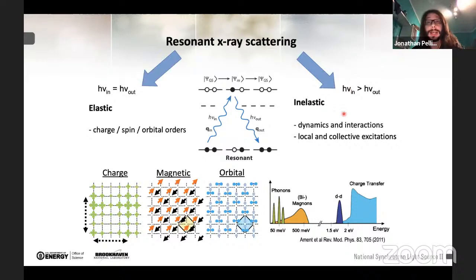On the other hand, when we perform resonant inelastic X-ray scattering, so the incident energy is higher than the outgoing energy, which means we leave the system in an excited state, we can investigate the dynamics and the interaction present in the system, as well as the local and the collective excitations. And due to the pretty complete interaction of X-rays compared to other probes, we can investigate all of the electronic degrees of freedom. As I said before, we can investigate the charge, the orbital degrees of freedom, the spin excitations, so the magnetic degrees of freedom, and lattice vibrations.